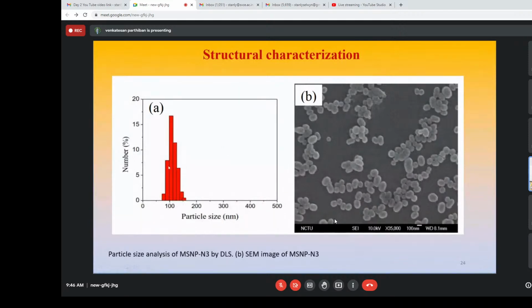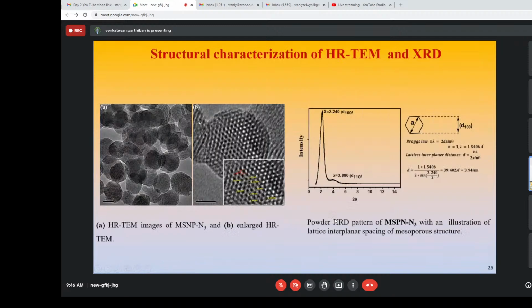After that, we check the DLS and SEM image. We can see the particle size is around 100 nanometers. After that, we further confirmed with the TEM image. We can see the TEM image shows a uniform hexagonal structure. Further, we confirmed the uniform structure, like the pore volume, the surface and hexagonal diameter, everything is the same or maybe different. So we confirm almost the same, and further we check using the XRD pattern. Between the TEM image and the XRD data, we see an almost similar pattern in the surface diameter.